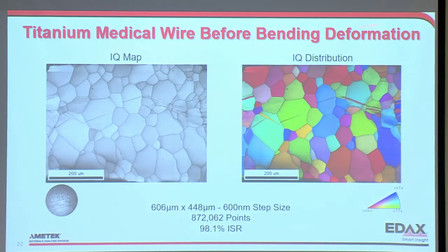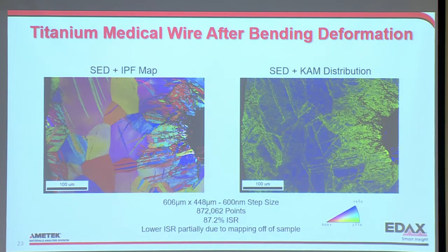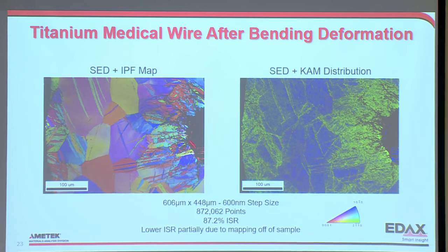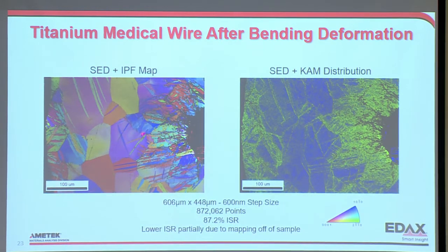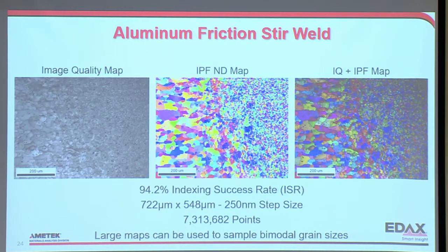This is a titanium wire before bending, and you can see it's great results. And then after bending, once again, great results. The indexing success rate was 87%, but we've got some area out here that we're not even using. That's off the sample now, and we're getting some voids in here, cracking, so not surprising.